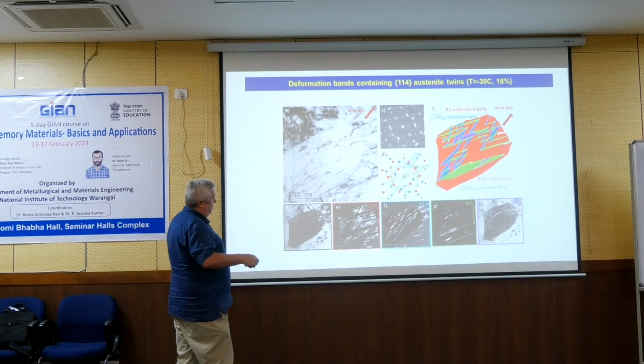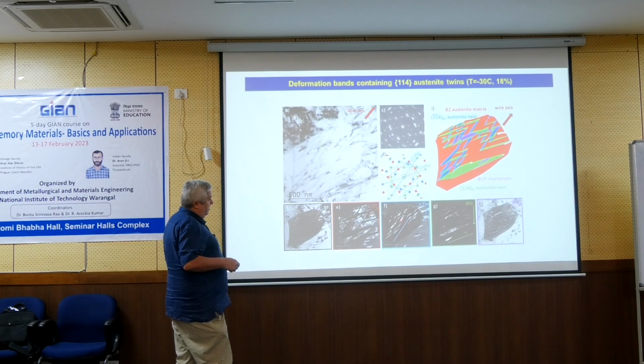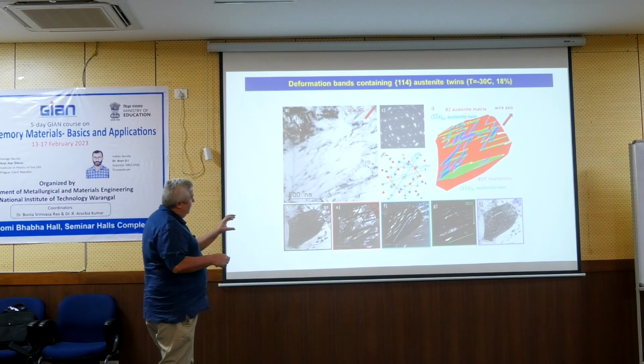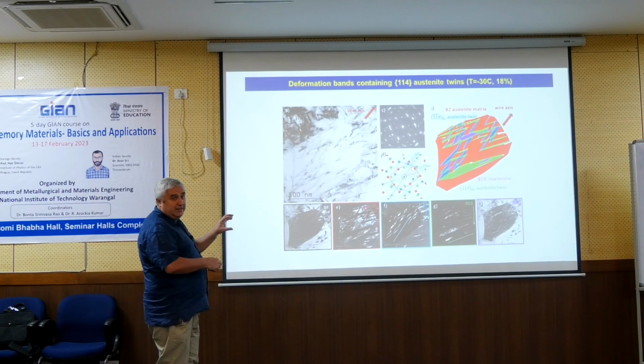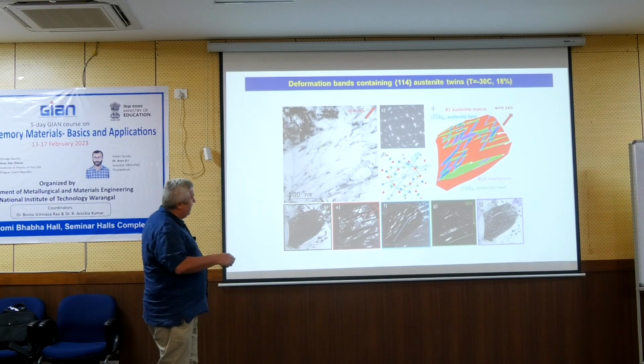So if we perform what is called dark field analysis, when we visualize this grain with the diffraction from the particularly oriented austenite, this is the blue twin, this is the green twin. So we see only the twin lattice which is oriented. These are the diffraction spots in which we did it. So if you did it with these diffraction spots, you would see the lattice which is oriented, and this is arranged in two bands. If you take the green one, you will see this lattice. If you take the red one, which is from the matrix, the bright would be only the matrix. Is it clear? So with that, we can understand how the austenite is oriented within this grain.